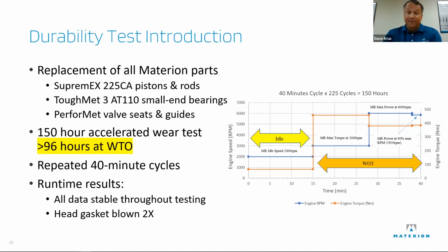So you run for about 15 minutes at idle and then hit wide open throttle maximum torque for 13 minutes, then do another 12, 13 minutes at max power and then drop down to 90% of max power to go through the cycle and repeat that 225 times. It's a brutal test for an engine and not something you would put racing materials through normally and expect them to make it.